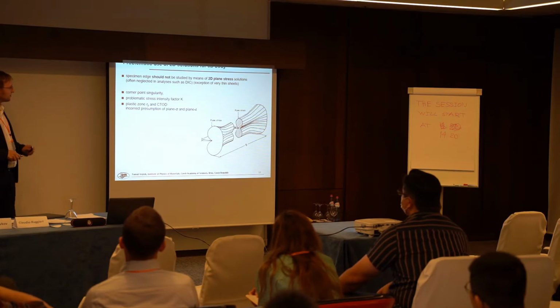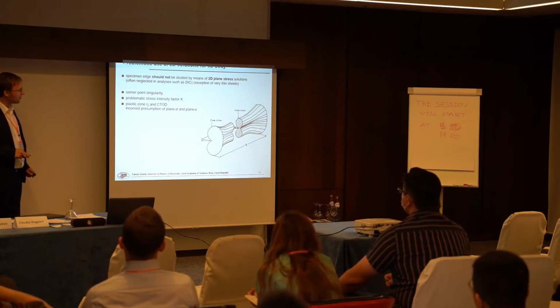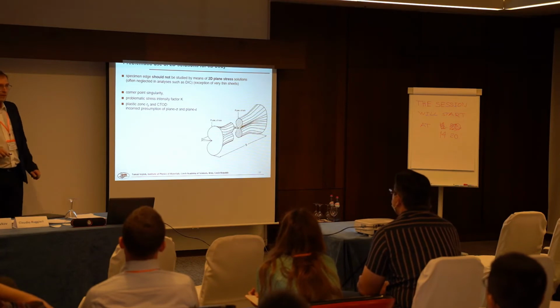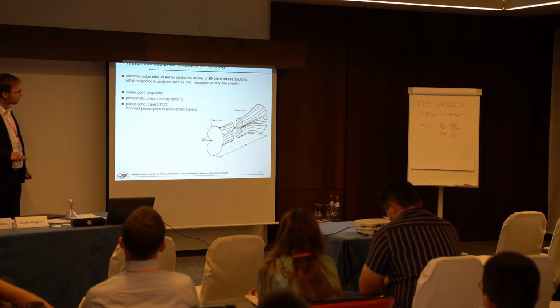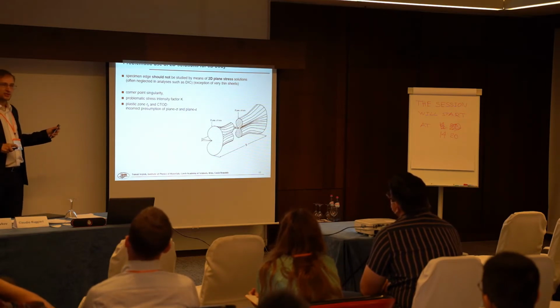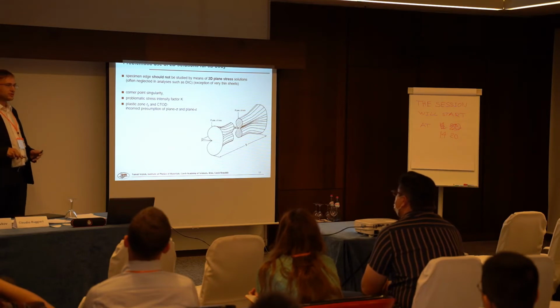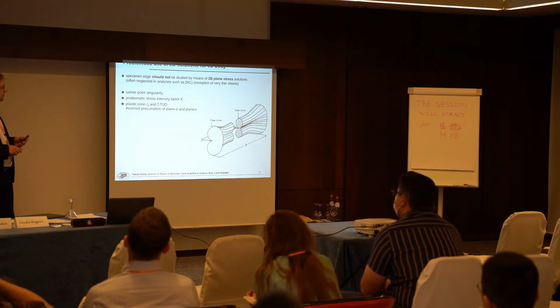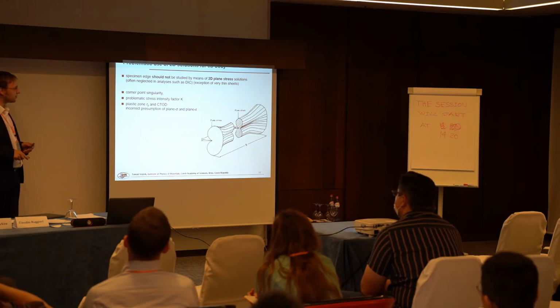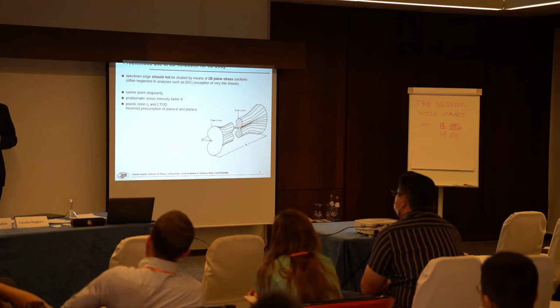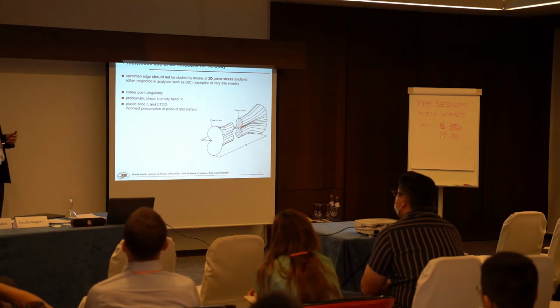There's not enough time. But just to show, I think most of you have seen this picture before. The problem is that if we have a specimen that is cracked, at the edge we usually presume plane stress state. But the problem is that we model what is going on by a two-dimensional model, assuming plane stress, and this is a different situation because in three dimensions we have a corner point singularity and the solution is different. So actually the plastic zone and all of the other things we study, especially for example, using the digital image correlation method, it's not actually correct. We should